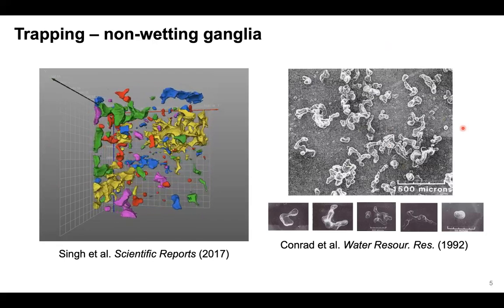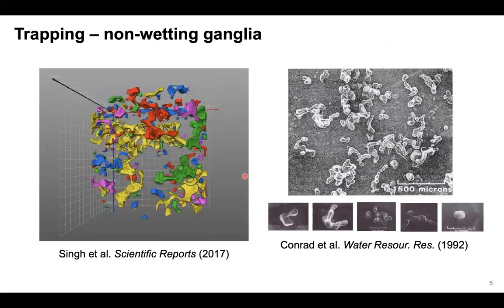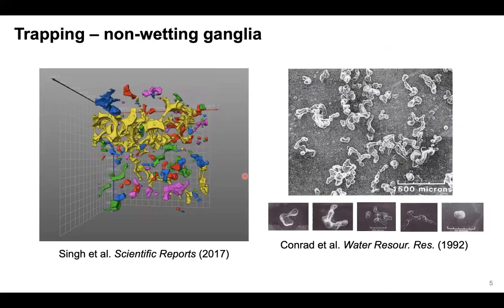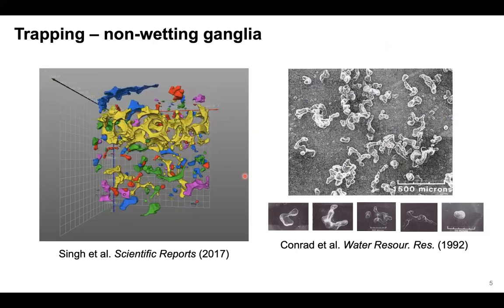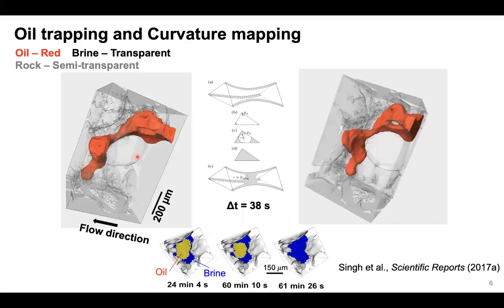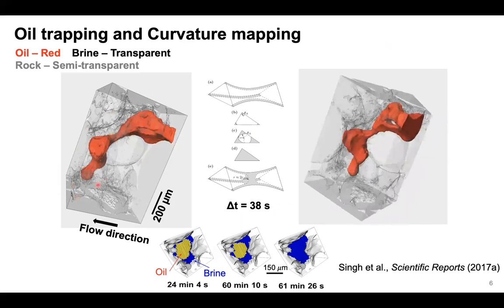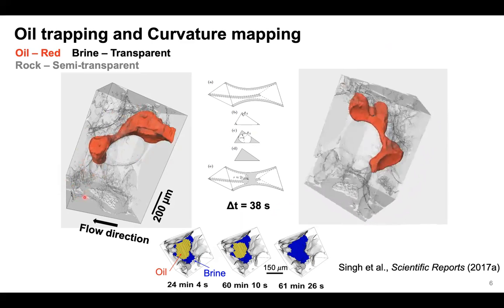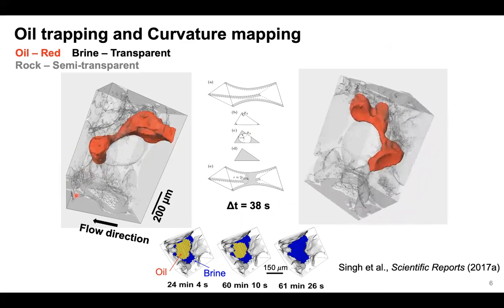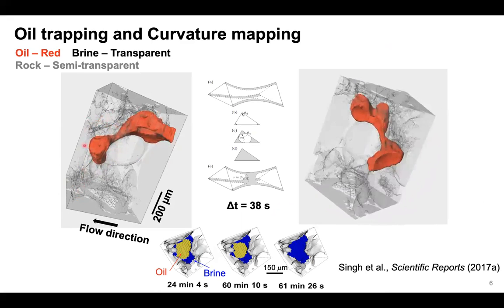These techniques were mostly destructive in those days, but nowadays we have the luxury of using tomography to image, visualize and quantify non-destructively. Now, because we have this time-resolved imaging from the synchrotron facility, we can also zoom into various locations and see how these oil droplets or ganglia get trapped. So here in this example, you see oil, and water is not shown. You can see as the water pressure is increasing, or if you keep injecting water, we get a pinch-off or snap-off leading to trapping in this pore.